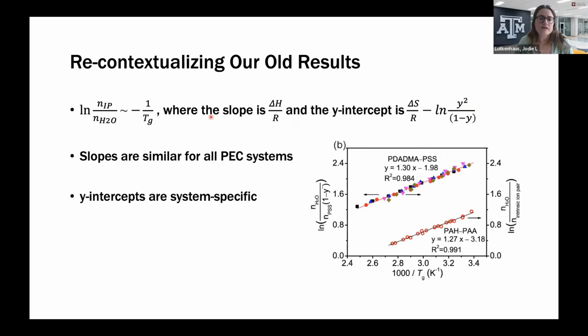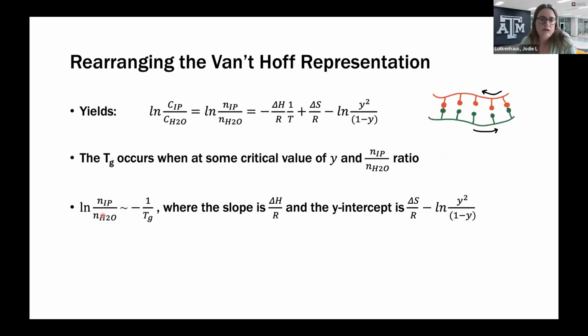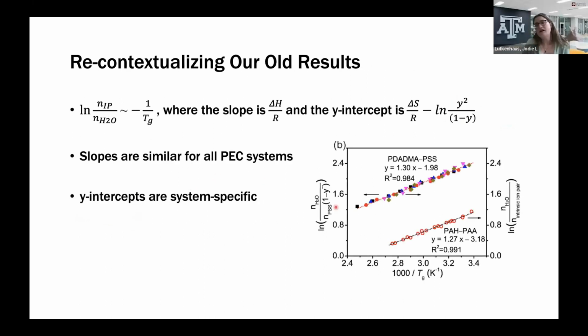And so by that interpretation, we may plot the data slightly differently. This interpretation is saying we could plot the natural log of intrinsic ion pair to water against -1/Tg. So we could do that. But it's equivalent to how we were plotting it before. Now, you look at these two different systems, they have different y-intercepts. Now we can discuss perhaps the different y-intercepts are due to differences in entropy and this Y value in the systems.